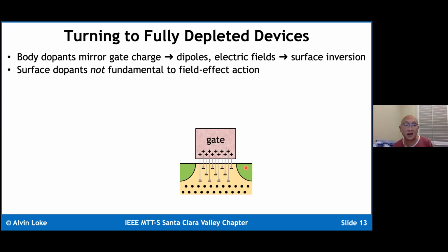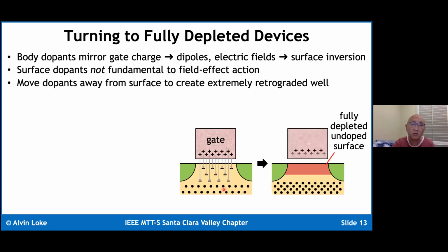Okay. Now, one thing I want to highlight here is that although our device textbooks always start by saying the MOSFET is formed by having a body with uniform doping, having dopants throughout this transistor surface, the key here is that surface dopants are not fundamental to field effect action. What is fundamental is setting up dipoles to create electric fields, which then causes surface inversion. What you can do is somehow move the dopants away from the surface, creating a region where you have no dopants, and essentially you have a very retrograded well, you can still have this dipole set up this way, okay?